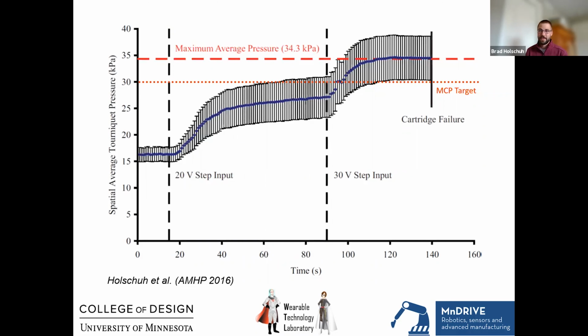So this is a figure showing pressure sensing of a shape memory activated tourniquet. On the x-axis is time, the y-axis is the average tourniquet pressure in kilopascals. The small red dotted line, right at about 30, is the spec for the spacesuit. It was 29.6 kilopascals. That level of counter pressure was the singular performance requirement for my PhD work in this space. This is one of the figures that actually appeared in my dissertation.